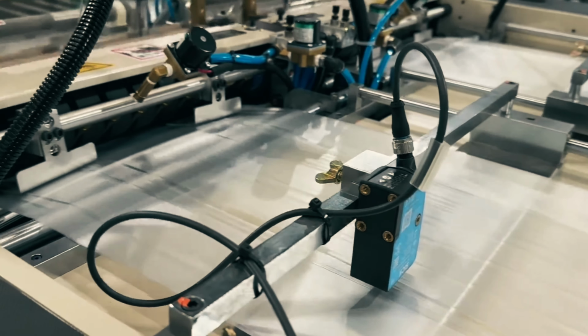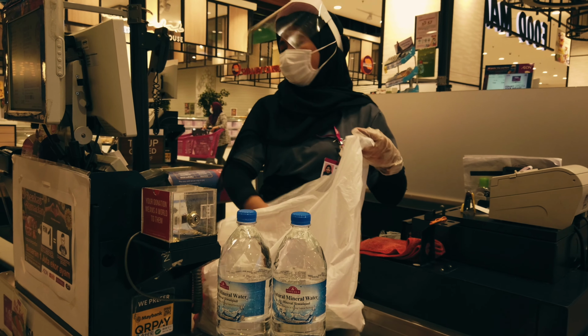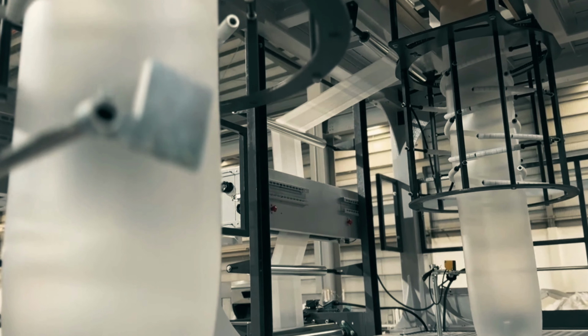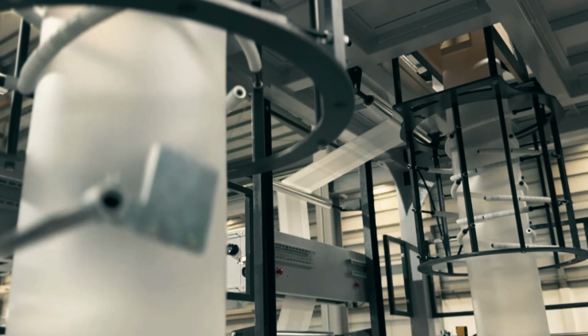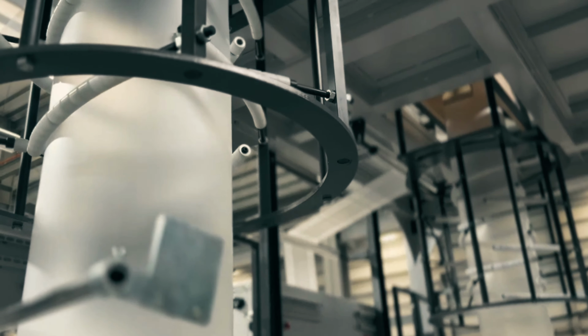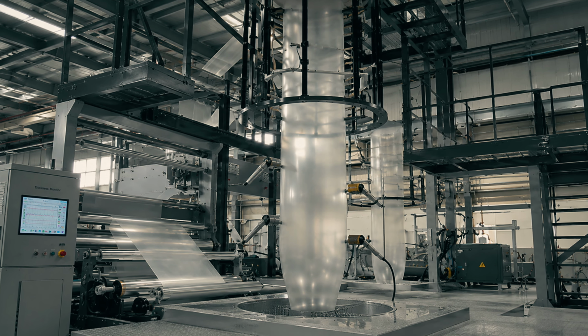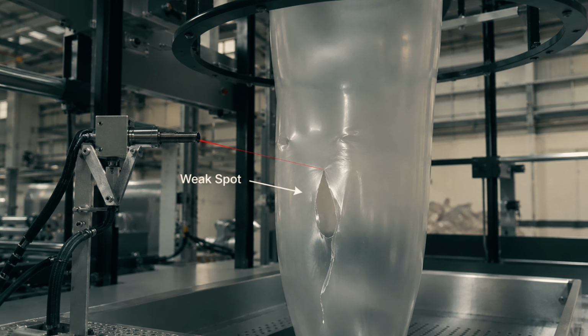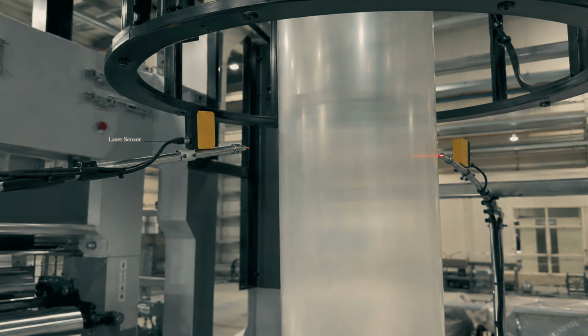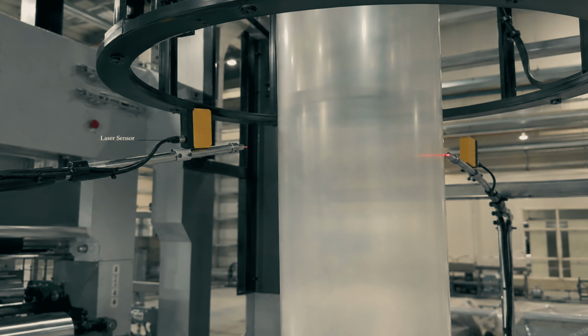The part that surprises most people: the plastic in a typical grocery bag is stretched so thin during the bubble process that it's often under 20 microns thick, thinner than a human hair. Yet the way the polymer chains align during that stretching is exactly what gives the bag its strength. If the bubble cools unevenly, the bag tears the moment it's loaded, which is why factories monitor bubble thickness with laser sensors in real time.